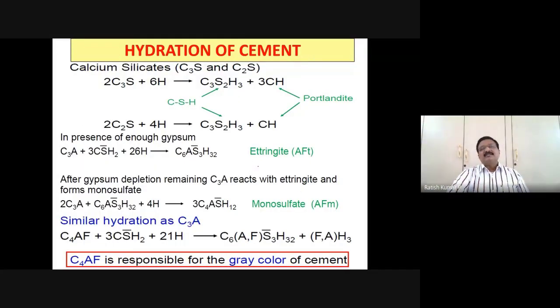The hydration of the cement, if I put it very quickly: the tricalcium silicate and the dicalcium silicate are going to produce CSH gel, as you know, and also portlandite, which is nothing but calcium hydroxide. And this is basically responsible for the strength, and it is more responsible for the durability point of view, because of the belite type of cements, the dicalcium silicates, which are called belite cements. Of course, we are trying to do a lot of research on belite cements.